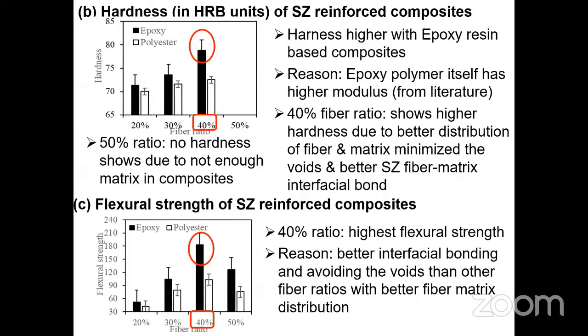The 40% fiber ratio shows better hardness due to better distribution of fiber and matrix, minimizing voids and providing a better Sansevieria zeylanica matrix interfacial bond. At the 50% ratio, no improved hardness shows due to not enough matrix in the composites. So 40% is the best ratio for this test method.